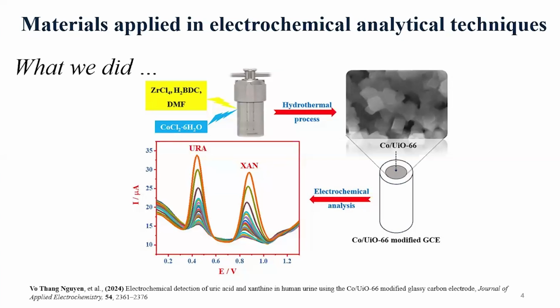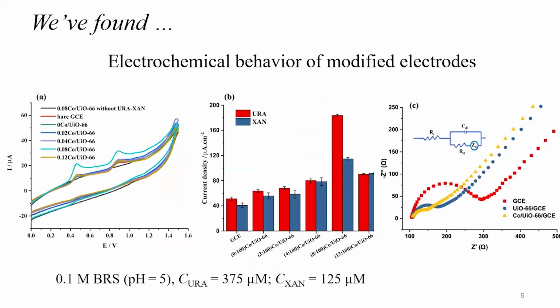In this example, we synthesized cobalt-doped UiO-66 materials, and used that as an electrode modifier to simultaneously quantify uric acid and xanthine in the sample. We found that with this modifier, we can clearly detect both analytes, especially at the optimal cobalt content in the sample. We can obtain the highest peak current, which means that we can detect this analyte at that concentration, but the other electrodes can't.